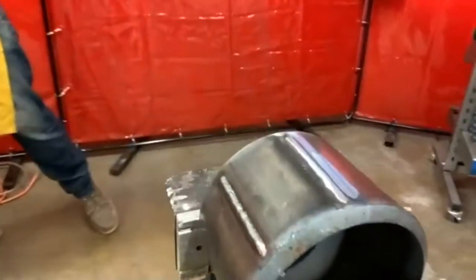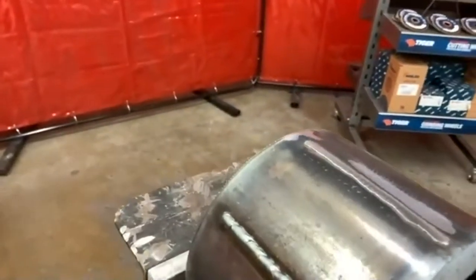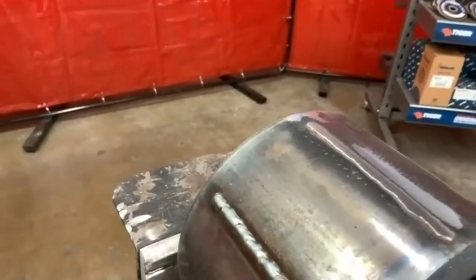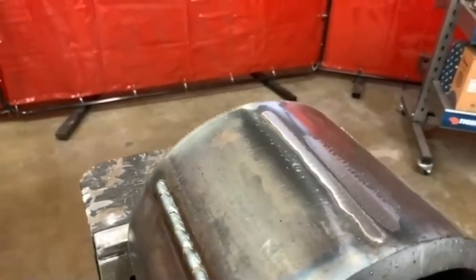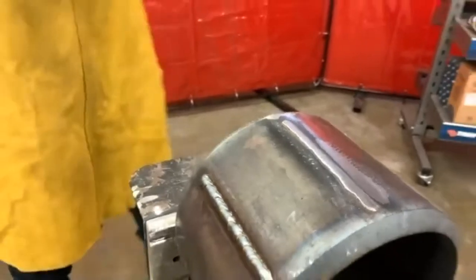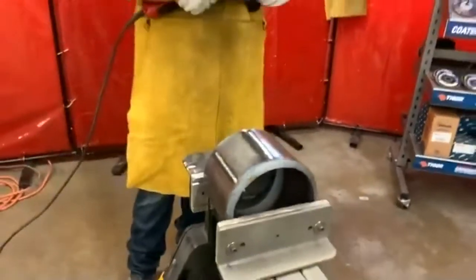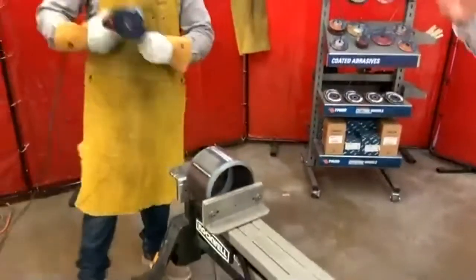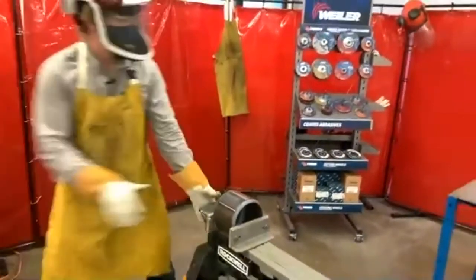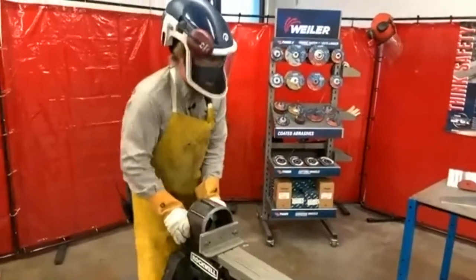Right, and it's interesting, right? Because you can see, as you started to get through that weld, where the disc was starting to come in contact with that mill scale. You could see where it started to slide a little bit more. You were losing that aggression until you started to work through that mill scale and crack through to the bare base metal.